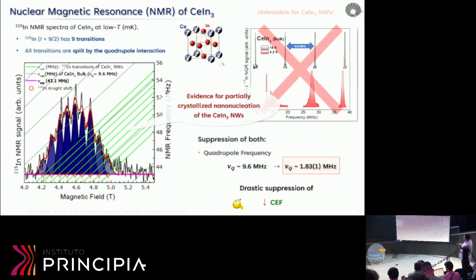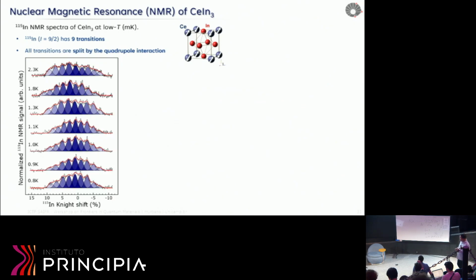Also, because we had to change the parameters here to explain the spectrum, we had to allow these Euler angles in plane. It gives us some suggestion that our nanowire is not 100% single crystalline, not yet. We have to improve this. But other than this result, we already had a very important result here.